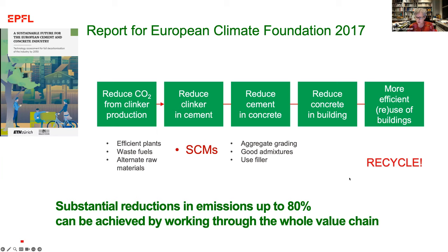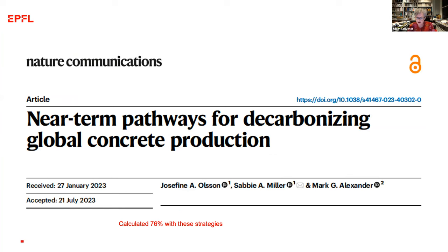And we demonstrated here that if we put all these things together, even using existing technologies, we could have very substantial emissions reductions, up to even 80%, by working through the whole value chain. And this was confirmed by a more recent study, which came out in Nature Communications, which calculated with the same kind of strategies, a possible reduction of 76%.